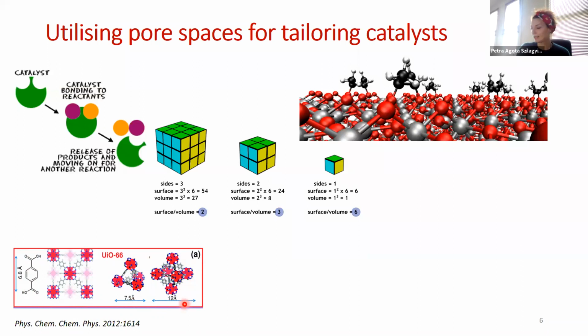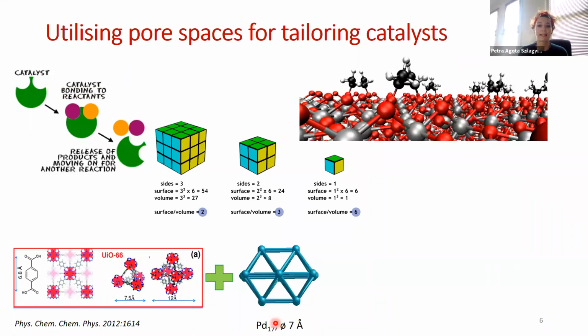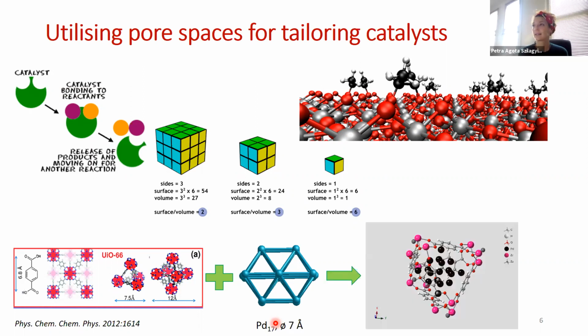So if we say that, well, let's use this MOF, for example, as the template or the mold for the growth of our clusters, we can think of maybe a metal cluster like this. This is a palladium 17, made up of 17 atoms, and it's 7 angstrom in diameter, so it should fit nicely and snugly inside the pores of this metal organic framework.